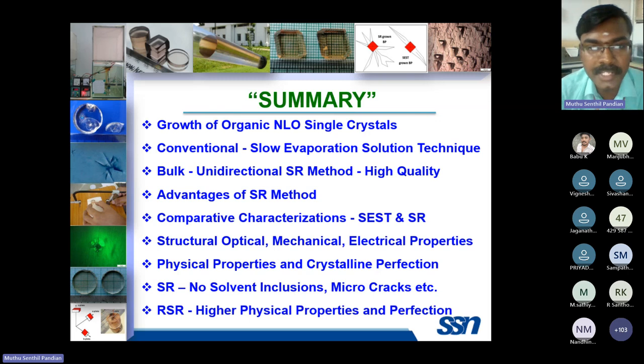So the final summary of my lecture is we have selected several technologically important nonlinear optical and ferroelectric single crystals. Initially, we have grown the crystals by this SEST method, the slow evaporation solution growth method. In a very small size crystallizer, we have grown a large number of single crystals and we identify the direction of the crystal using single crystal X-ray diffraction.